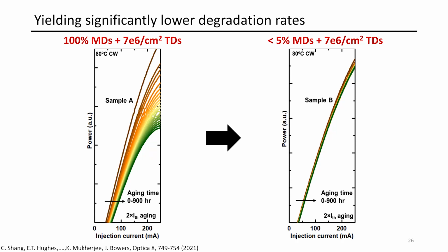So we simply displaced where these dislocations were forming. We didn't change the number. We didn't change the density. We understood how they form. And we harnessed indium pinning to stop this from happening.